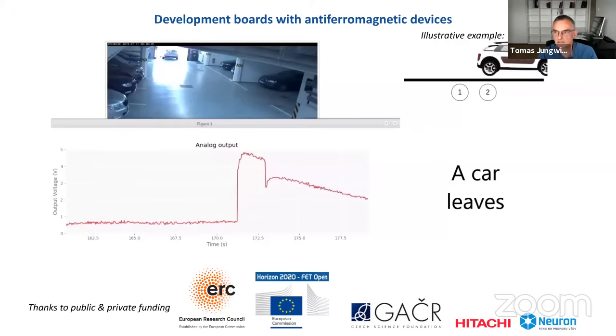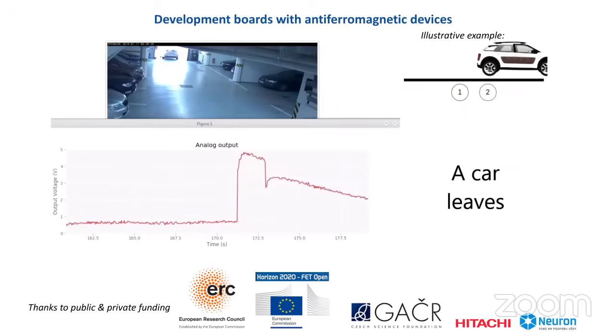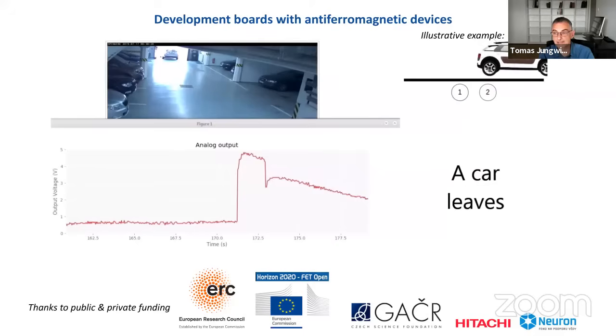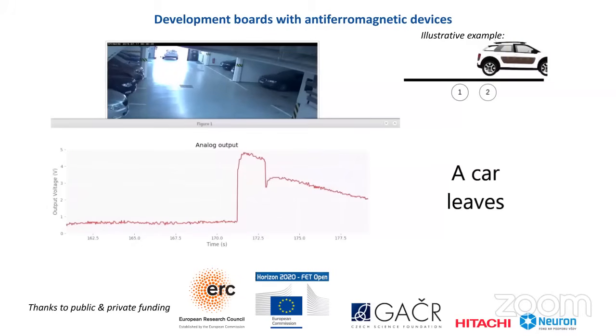Right, but in iron rhodium, the ferromagnetic phase is stable at high temperatures, about 100 degrees above room temperature, and then the antiferromagnetic phase is stable at lower temperature. Right, but it can be at the same temperature optically also. It can also be switched optically at the same temperature, on a time scale which is not really compatible with lattice expansion, lattice heating. I don't know if it's fully understood yet or not, but I think it was demonstrated experimentally in this pump probe experiment.